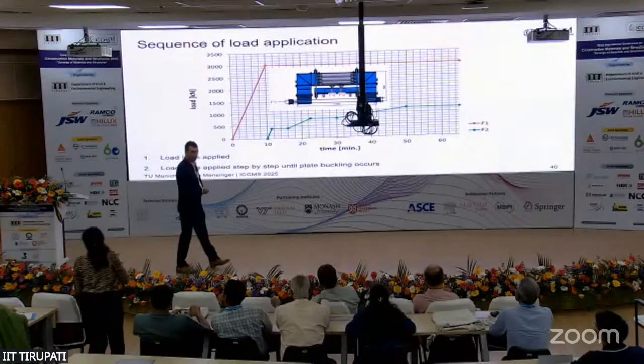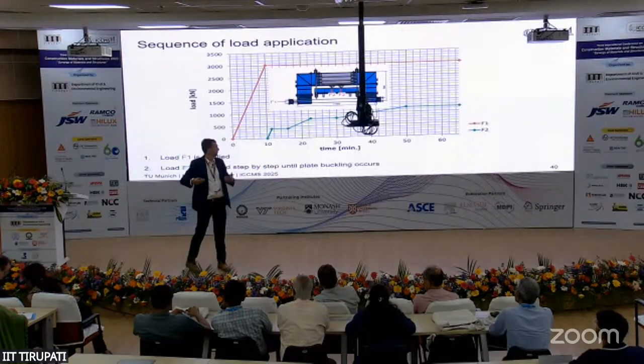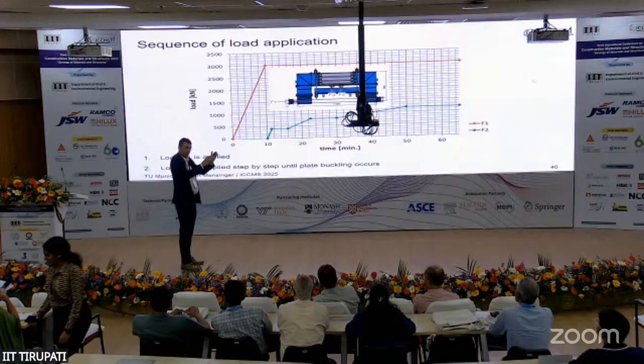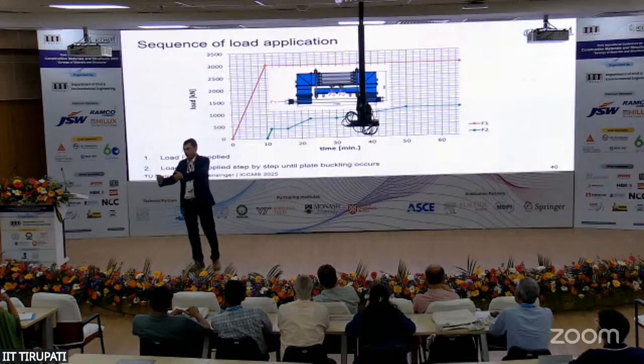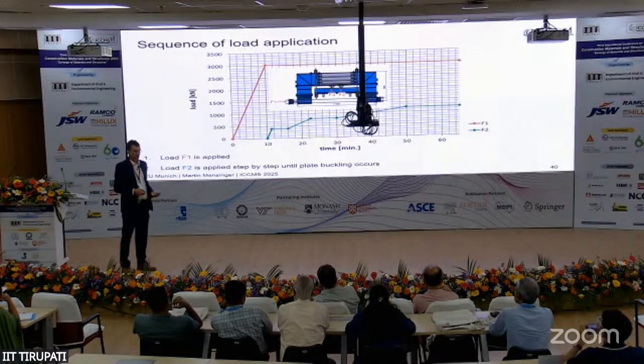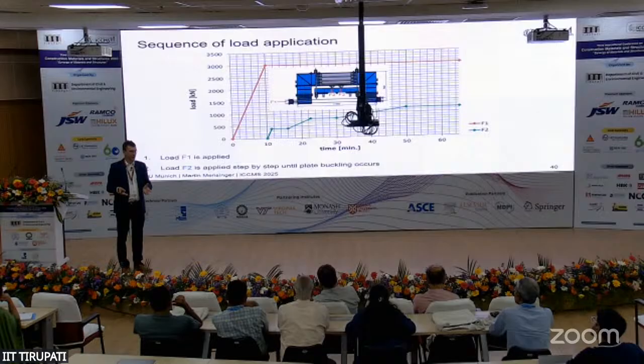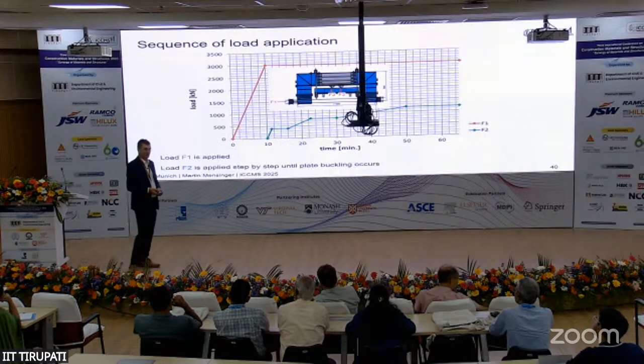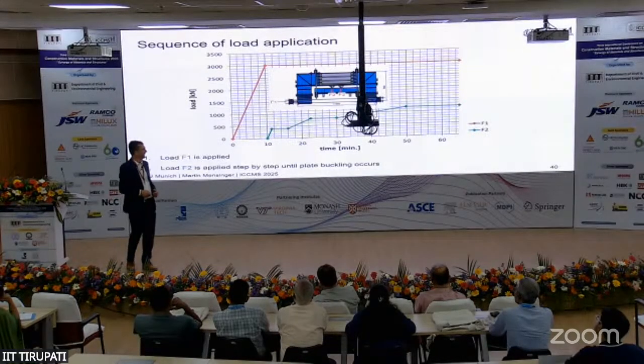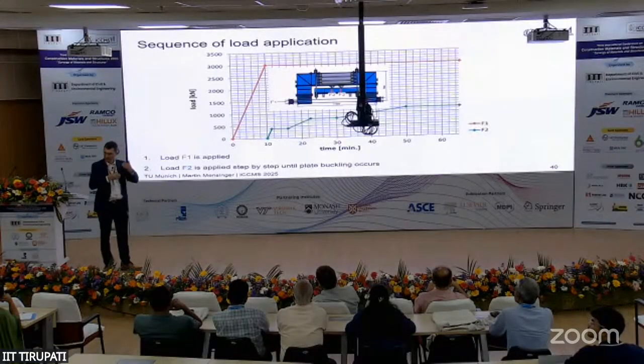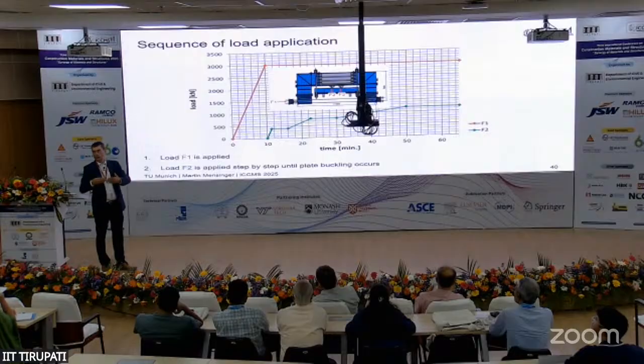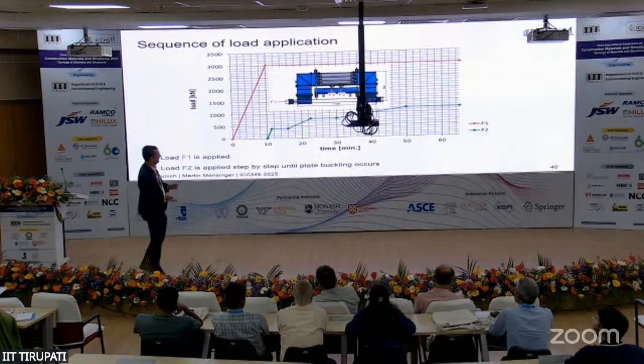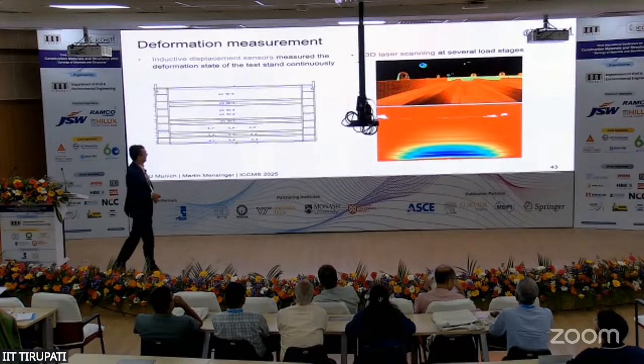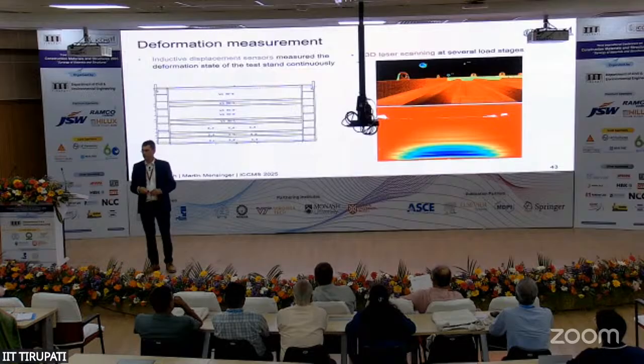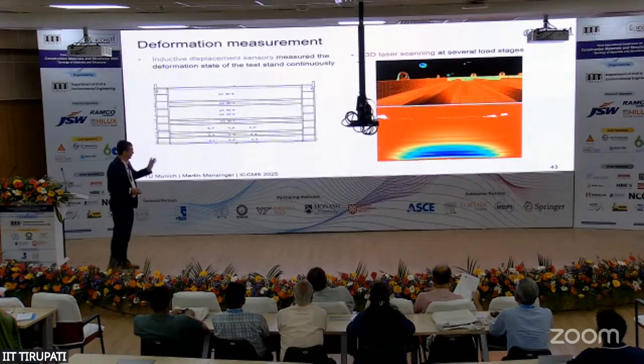During our first test, we applied the longitudinal load in the first steps in X direction. This is the force F1. So the bending moment was introduced first, and after that we introduced the normal force in the cross direction, which is not happening like that in real structures. In real structures, both occur simultaneously, but we feared that something would happen because this is a dangerous test. It's a large test with really high forces, so we were a little bit cautious. That's the reason why. And later on, we checked if this load sequence has an influence on the upper load limit, and I will talk a little bit later about that again. And also, we measured again the initial imperfections of our test specimen via laser, and we used